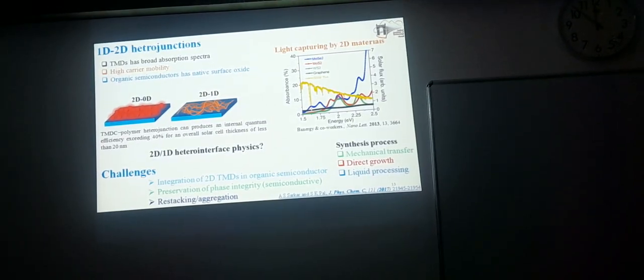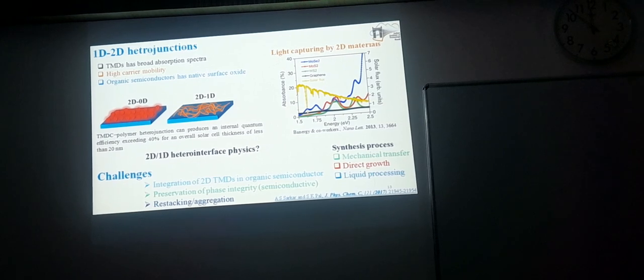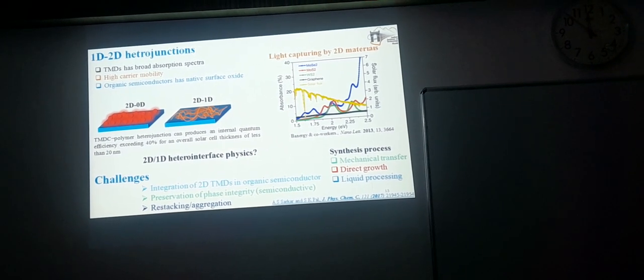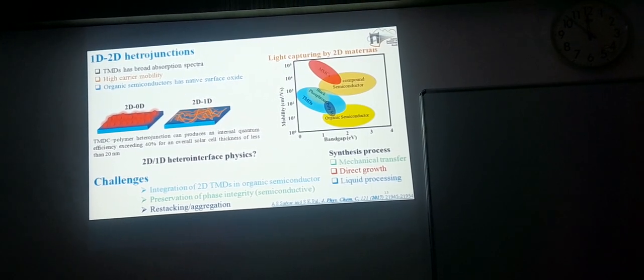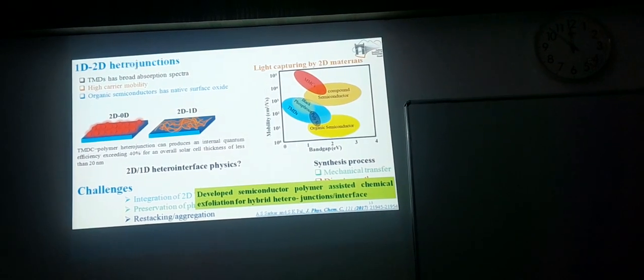Another reason is that, as I mentioned before, this is a highly absorbing material. The absorption cross section is super high. If you look at the different materials, especially the thin layer of this transition metal dichalcogenide, it can absorb 10 times more sunlight than existing silicon. So that was another motivation of this kind of work in the last few years of my PhD research.